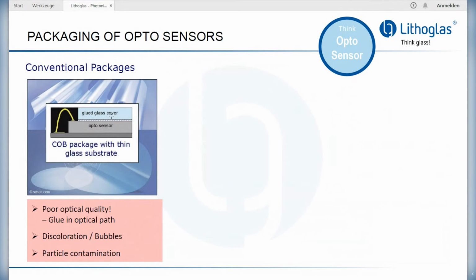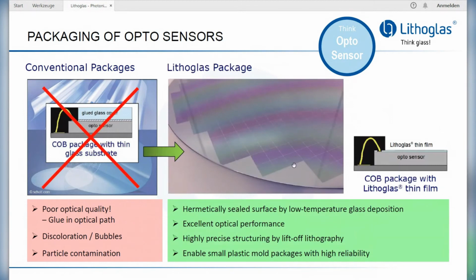We actually have a front-end process to deposit a thin glass film. It's a low temperature glass deposition process below 80 degrees Celsius. So we can use a simple lift-off structuring to keep one path open. And you could, for instance, make a very simple plastic mold package. But since the glass film is directly sealing the opto sensor, you will have very good reliability and very good optical performance.